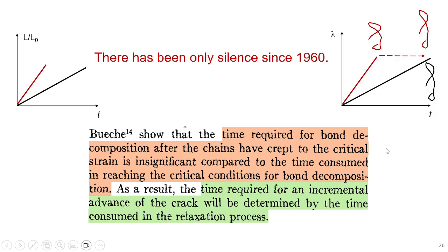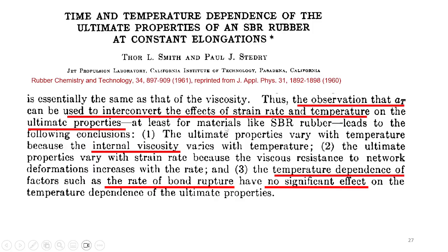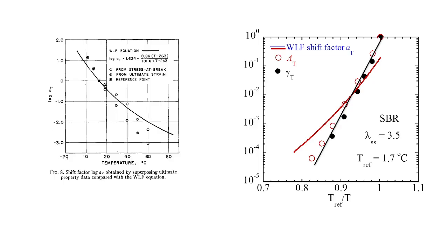No paper ever repeated this. How to comprehend this? Maybe they didn't figure out this is the reason. In any case, the same paper speaks about nothing else. Look, the last one says the temperature effect on rupture has no significance. So basically, they are aware chains can break, except they are also insisting that chain breaking is not the dictating process. The system is mostly spending time reaching the stretching, which is a big violation of what affine deformation is, which actually is quite accurate. I will have experimental proof for you. In any case, this is the same paper.